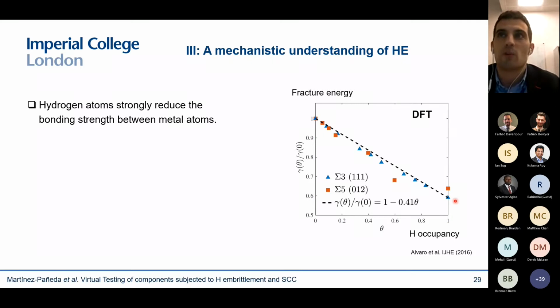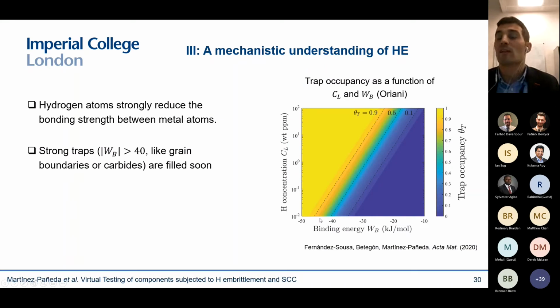So then the next question, of course, is how much hydrogen is actually in my grain boundary? Because if the occupancy of the grain boundary is low, then there must be other mechanisms that are playing a role. And the answer to that comes from the thermodynamics of trapping. So we know that Oriani allows us to plot the lattice hydrogen concentration as a function of the binding energy. So how energetically favorable is it for the hydrogen atom to sit in that microstructural trap, and also versus the trap occupancy, right? How full the trap is going to be.